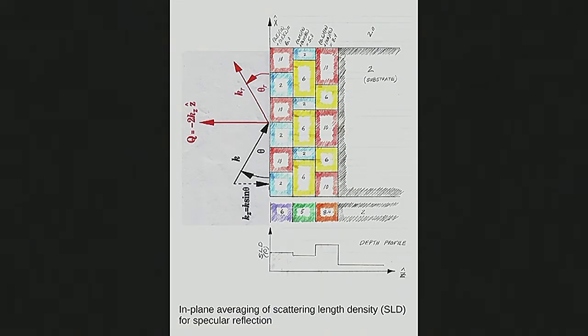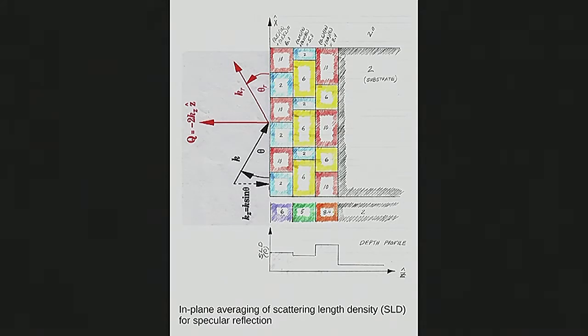If we maintain this geometry with the sample as a layered film-like structure on some big macroscopic substrate that's as flat as can be made, then when we do the scattering under the specular condition, we're getting information along the surface normal — we're doing a depth profile. It's like an archaeological dig into the strata to see what the composition is as a function of depth. The momentum is conserved along the in-plane directions, and what we get is the average scattering density in-plane.